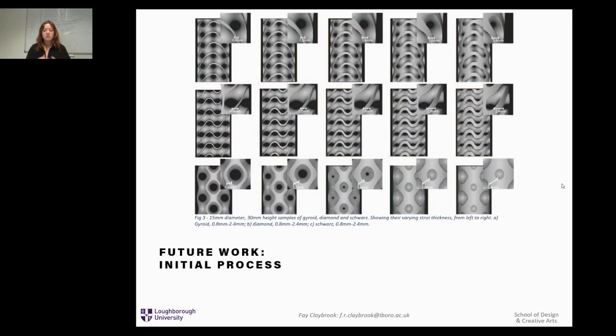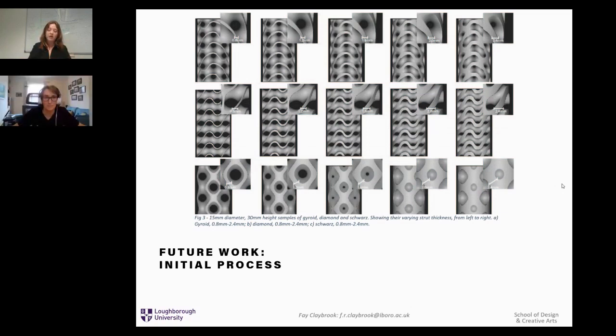So you can see as the strut thickness of a TPMS structure gets wider, the holes and gaps that are designed in them get smaller. So this could possibly influence the collapsing of these arches and the loading capacity. Then the analysing of this data is still being managed to ensure that the correct guidelines and the eventual database that will be formed from these structures is going to be reliable and able to be replicated into an insole from the pressures that the structures were capable to withstand on the uniaxial loading machine.